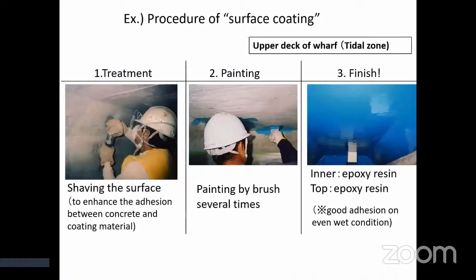This slide shows one example of the procedure of surface coating. The process has three steps. At the treatment, shaving the surface to enhance the adhesion between concrete and coating material. At the painting, painting by brush several times. And finish.